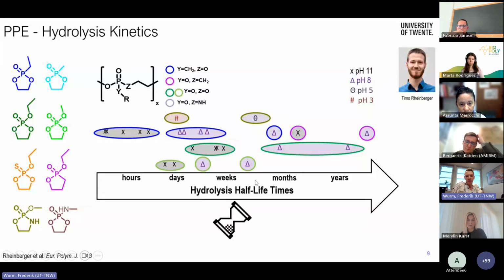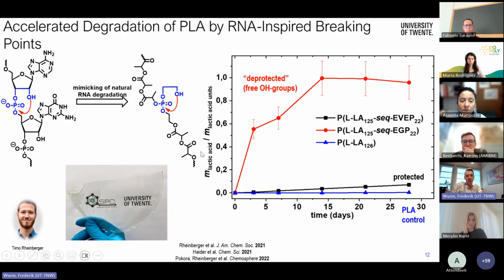We see here the postdoc Timo on the team did this already before, looked at hydrolysis half-life times. And sometimes it's difficult to see from the first glance of the monomer structure. Some of them hydrolyze in hours, others are stable for years. And that allows us also to tune here the application. And then inspired by that, we put it previous to the project already in PLA. So I mentioned PLA is very recalcitrant in seawater, but when you put these breaking points into PLA copolymers,